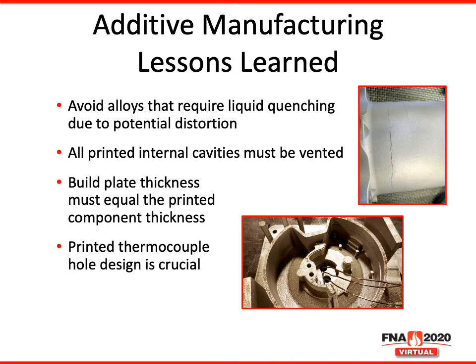Okay, some lessons that have been learned during the process. First, we have to avoid alloys that require liquid quenching due to potential distortion. All printed internal cavities must be vented to avoid binder powder blowout. The build plate thickness must be equal to the printed component thickness. And then printed thermocouple hole design is also crucial.